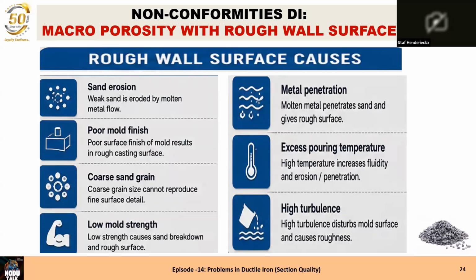We have other possibilities. Sand erosion: weak sand is eroded by molten metal flow. Let's say that's a rough surface, but it's not a porosity as such, and it will not happen in the center of a section. A poor mold finish, that's again the surface, but it's not okay, and that will be taken up in the next session. Coarse sand grains give a rough surface, of course. Low mold strength gives a rough surface.